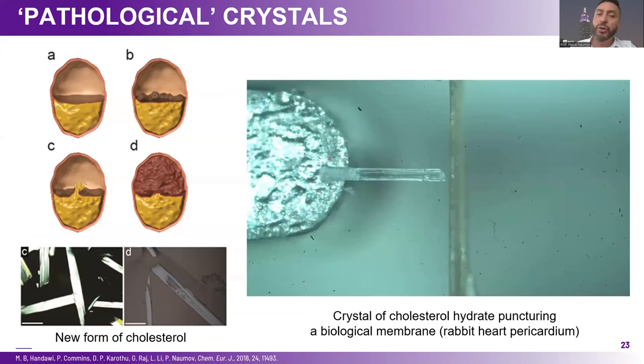Now, I want to show you also something about pathological crystals. So there are crystals that form in our body and are not good for our health. One of the cases is related to the myocardial infarction, or a heart attack, where it has been postulated back in the 60s that when you have a plaque like this, what happens is that in this gooey kind of environment, you have crystallization of the cholesterol crystals, which can puncture the artery, and then you have a spill, and then you have a heart attack.